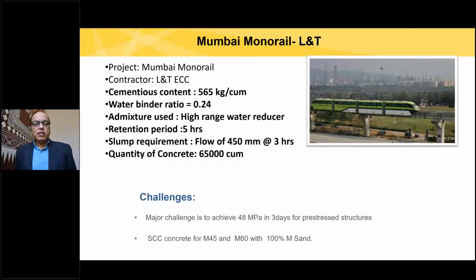Therefore, to achieve this very low water binder ratio, we have to use high range water reducers. But still, the slump retention period that was required was 5 hours. Slump requirement was so much. And what is the quantity of concrete? It is not just our laboratory concrete that we do just to showcase that it has this property. No, 65,000 meter cube of concrete should be made with this kind of property.